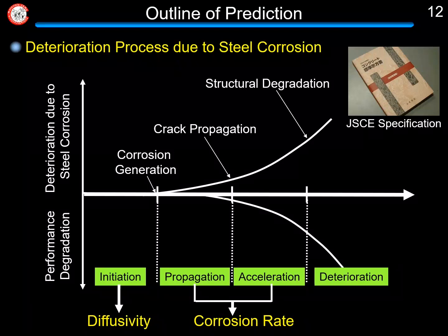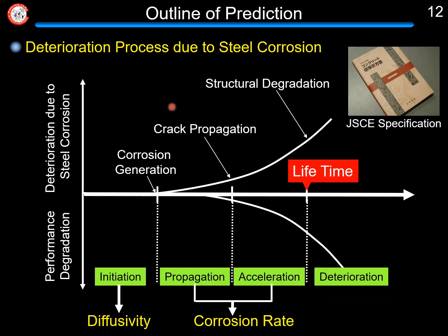Based on the experimental results I mentioned before, the prediction of the deterioration process was conducted in this study. This conceptual diagram shows the deterioration process of reinforced concrete denoted in the Japan Society of Civil Engineers Specification, Maintenance Edition. According to this specification, the deterioration process can be separated into initiation, propagation, acceleration, and deterioration periods. Especially, the initiation period is highly related to diffusion coefficient, and the propagation and acceleration periods are related to corrosion rate. Therefore, these periods are predicted based on the experimental results, and the lifetime is calculated as the sum of initiation, propagation, and acceleration periods in this study.